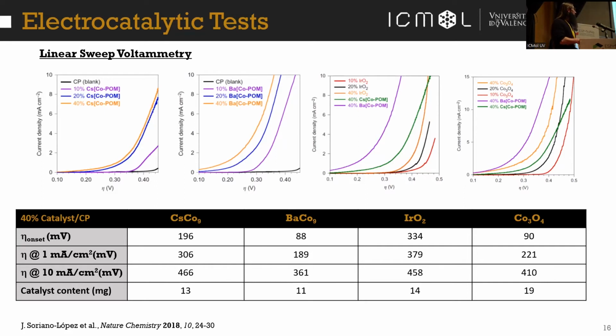But still, cobalt oxide was pretty active under these conditions, and it was blowing our minds, because cobalt oxide should not be stable at pH 0, and even the cobalt-9 should not be stable under these acidic conditions. Actually, we took cobalt-9 and put it in a 1 molar solution of sulfuric acid, and basically what you get is a precipitate, a white powder, which is the lacunary Keggin, and you have the cobalt ions in solution. So this was telling us that the carbon paste was not innocent under these conditions, because it was creating a hydrophobic environment around the polyoxometalate that was protecting it. So we continued with our study.